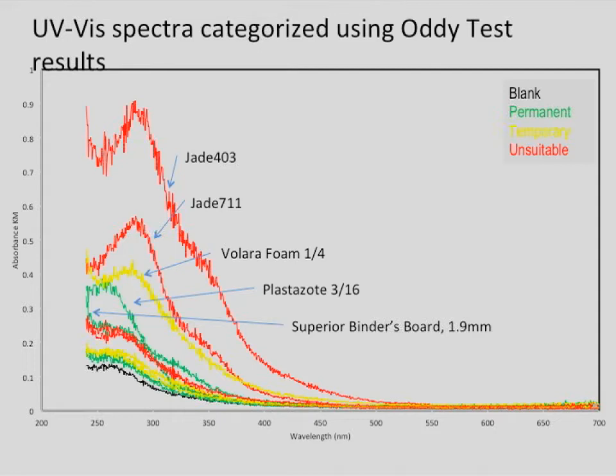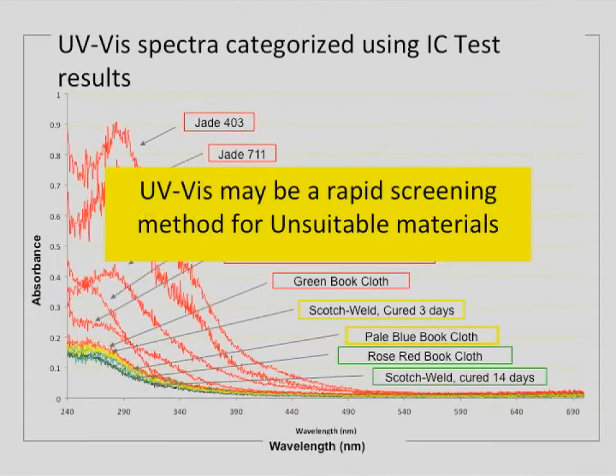And you can see that there's sort of no trend, right? The black line is the UV absorption of Whatman aged with just air, so it's our control, and then the rest are samples that we aged, or sorry, preservation materials we aged with Whatman. And there's sort of no trend when you use the Oddy test results. Whereas you see a trend when we look at the IC test results, and this is pretty clear.